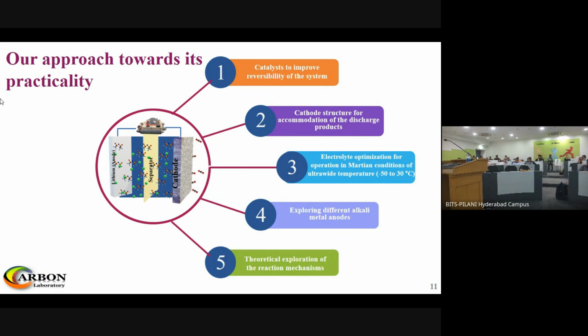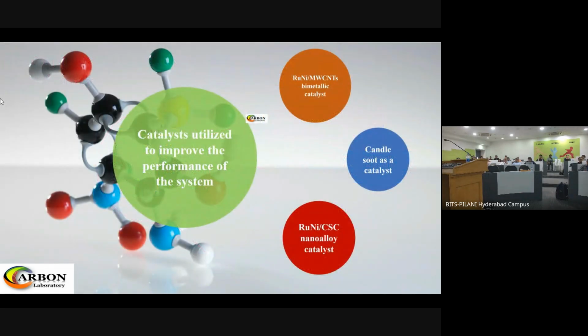So today, I will be focusing more on the catalyst part, considering the audience and the theme of the symposium. We developed different kinds of catalysts. One is the ruthenium nickel bimetallic catalyst, which we dispersed on multi-wall carbon nanotubes, generally used as a good support. And then in our group, we have been working on candle soot in different ways. We will compare the performance of pure candle soot as a catalyst to multi-wall CNT, and demonstrate that candle soot works better than multi-wall CNT. That's why we then switch from ruthenium nickel on multi-wall CNT to a ruthenium nickel candle soot nanoalloy catalyst.